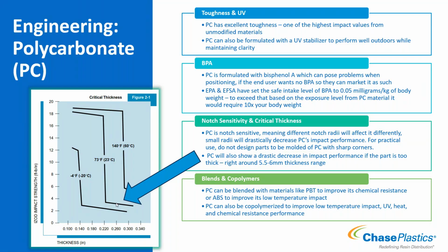Polycarbonate can also be, and is commonly, copolymerized with other monomers to improve low temperature impact, so it can be copolymerized with something like a siloxane. It can be copolymerized to improve UV performance, heat performance, and chemical resistance performance. So a lot of different variations of PC copolymers exist to help with performance in those key features.